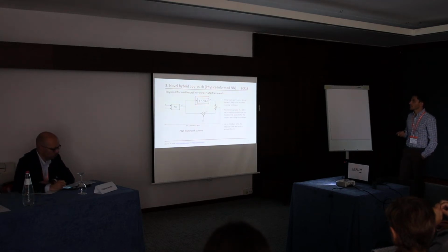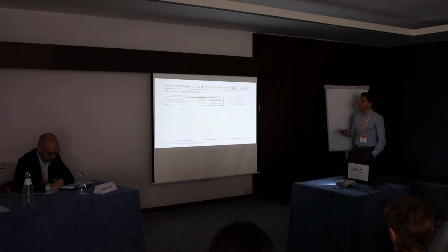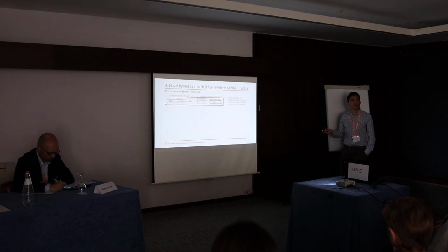Let's try to understand what is the condition that we need to apply to this neural network. Let's say we have a set of experimental data. This is the physics model. From CT scan, we can get all the interesting information we need: the square root of area according to Murakami, and the distance from the surface. Then we fatigue the samples, and we have the applied load and the number of cycles to failure. And if possible, we can also get some information about the actual killer defect through fractography.